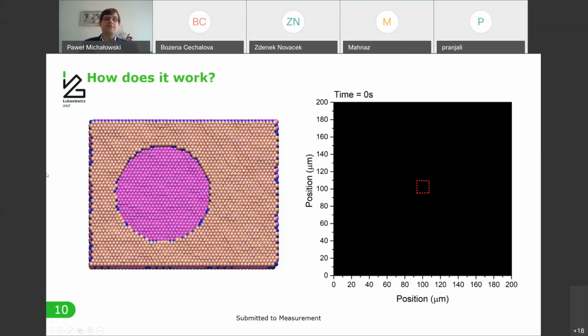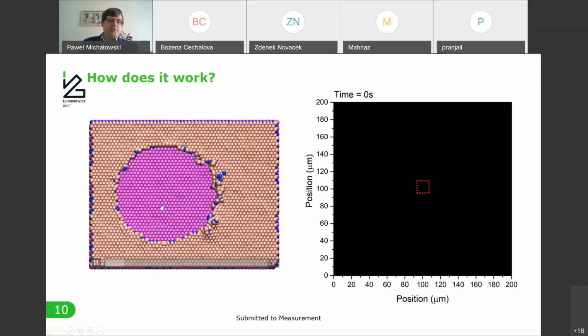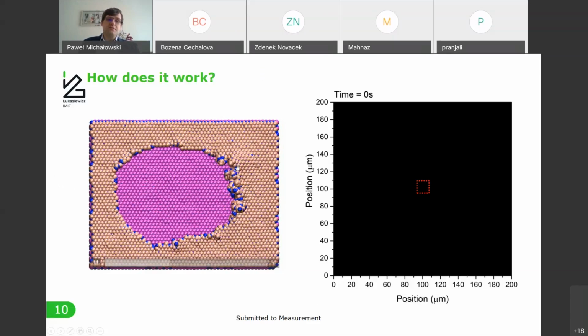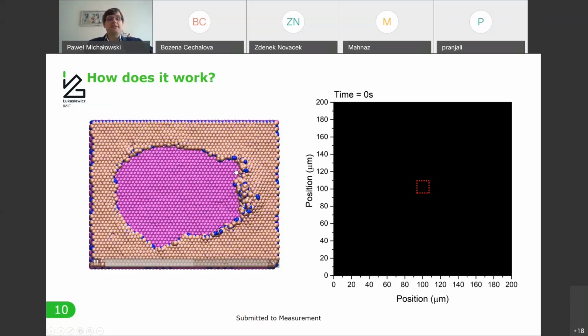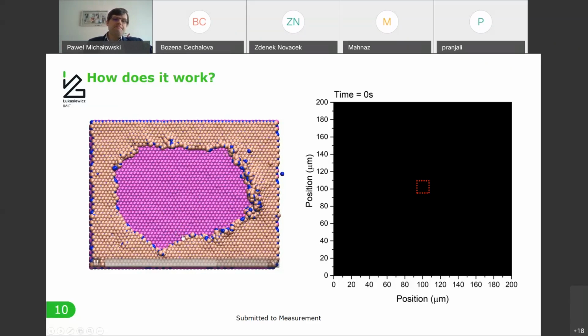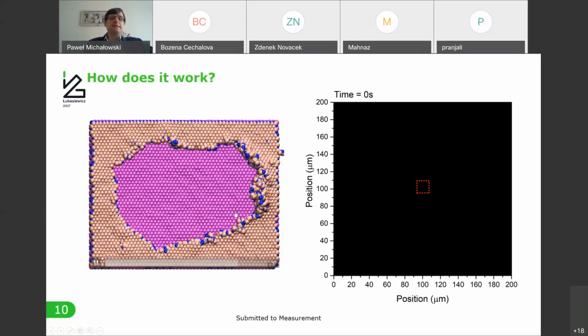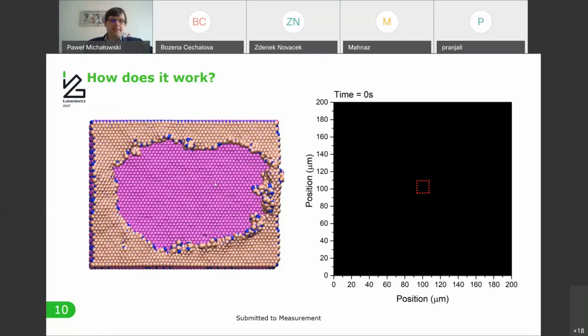To study it more, they also included in their simulations a large circular defect, as you can see from the top view here. And then the cesium bombardment is coming from left to right. Here you can see in the simulation that the bottom layer is not affected at all, but the top layer is sputtered, but in a very asymmetric way. As you can see, along the direction of the primary ions, it is much faster than in any other direction. And obviously, it is to be expected that no real sample is perfect. We still have some vacancies in the real sample, so that is how the sputtering process can start. However, from this simulation, this anisotropy is something that I really thought about, and I thought maybe we can repeat this experiment.